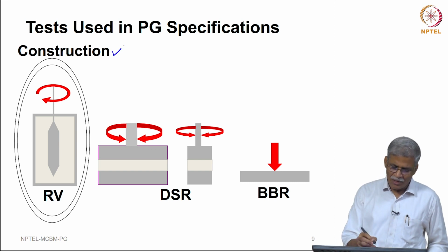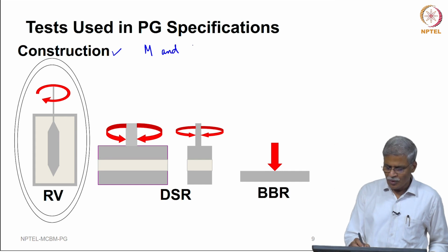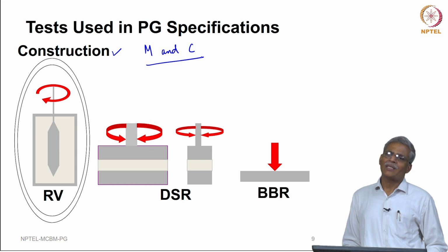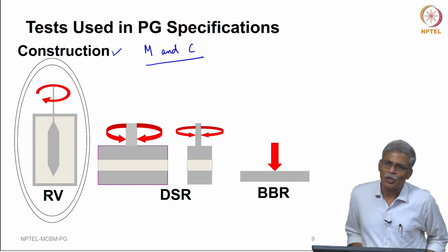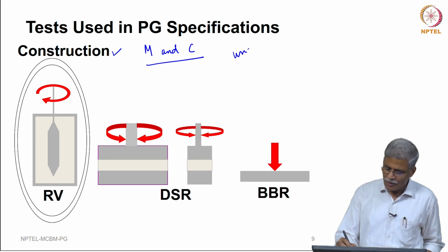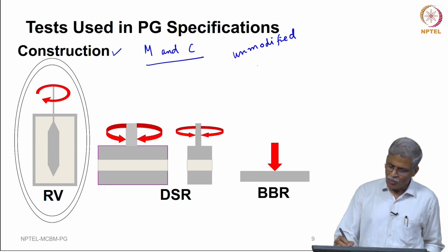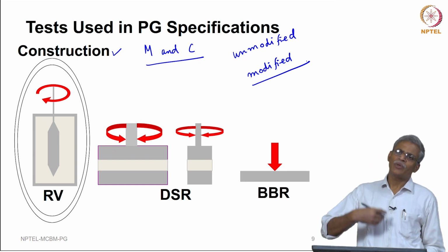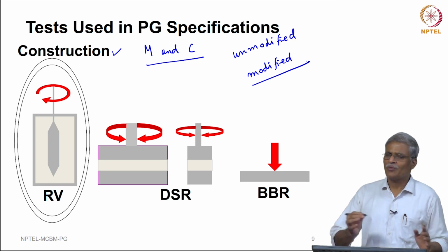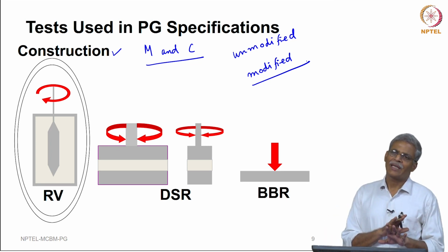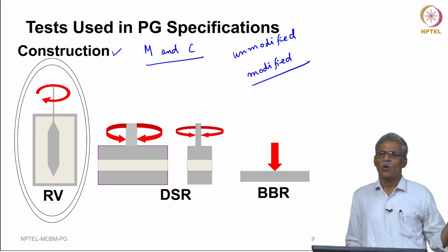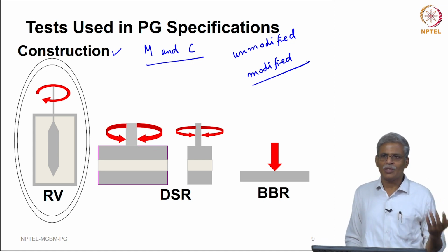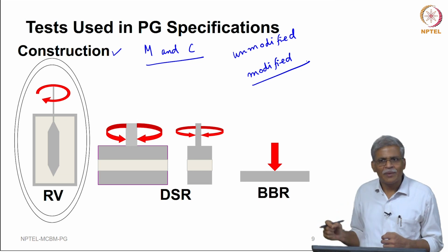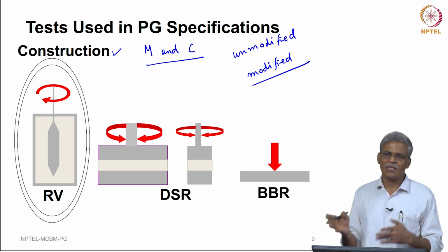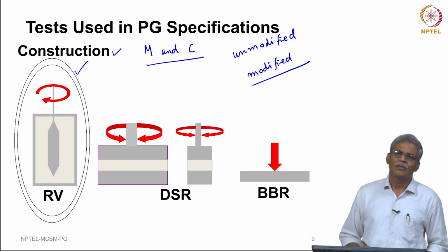So, we talk about construction. When we are talking about construction, we are talking about mixing and compaction. Now, precisely the mixing and compaction temperature that one should use for any types of unmodified and modified binders will be discussed separately. The issue is with the modified binder, and when PG was proposed, it was felt very much that the performance grade specification can completely mask the influence of the modifier. Over a period of time, after 10 to 15 years of use in the field, they realized that for modified binders, one needs a separate set of specifications and test methods starting from the construction site. So, that will be discussed separately.